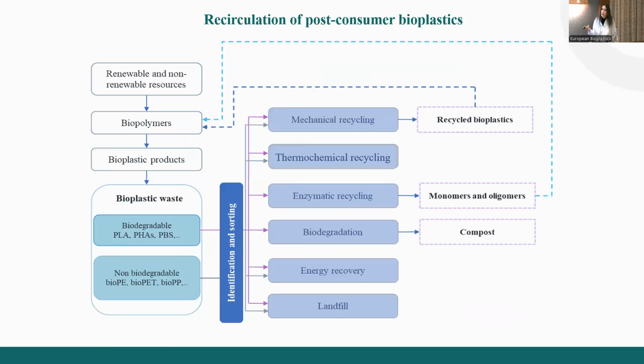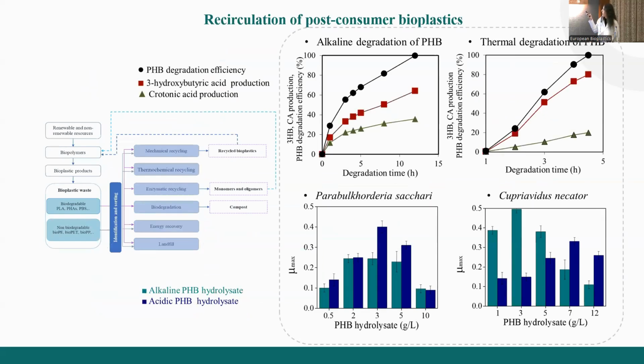Regarding the recirculation of consumer bioplastics, an end-of-life scenario should rely on the chemical and enzymatic recycling of bioplastics. This way, we can introduce new ways to transform waste into valuable resources. Here is an example of the alkaline degradation of PHB using sodium hydroxide solutions and the thermal degradation of PHB. In both cases, two monomers, 3-hydroxybutyric acid and crotonic acid, were produced. In the case of the alkaline degradation, we have a higher production of crotonic acid. We observed that when we used these hydrolysates in microbial fermentation as carbon sources, at higher concentrations of the hydrolysate, there was an inhibitory effect on bacterial growth and production of PHB due to the presence of crotonic acid.